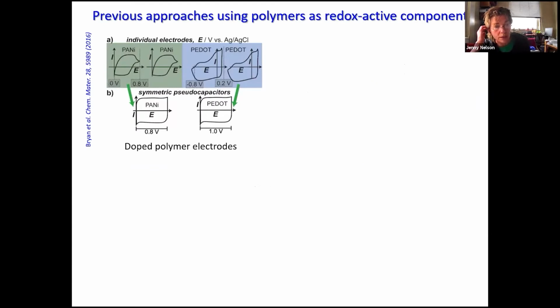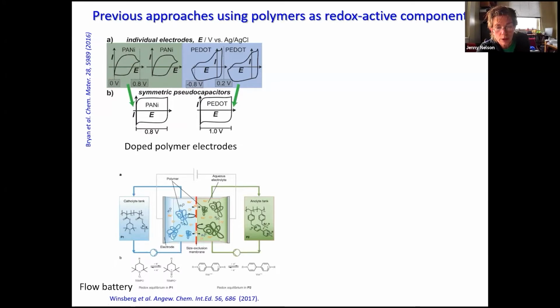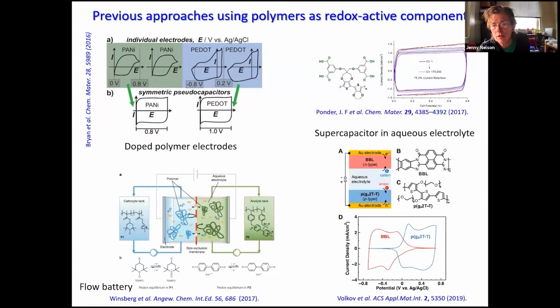Some approaches had been taken in the past literature to using polymers in storage devices. Doped polymer electrodes had been studied, things like PEDOT, where you have a dopant present and you charge and discharge the material, removing and reinserting the dopant. There's also been work looking at using polymers in redox flow batteries, which is interesting, but a very different direction. And closer to what we're doing, there have been a number of studies where polymers have been used in supercapacitors, and they're particularly interesting because of the compatibility of conjugated polymers with aqueous electrolytes. I give two examples here.